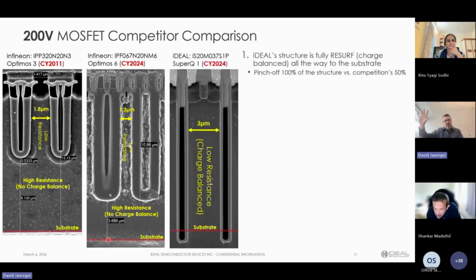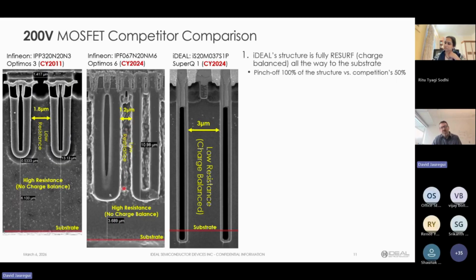Our technology, taking that 650 volt MOSFET structure, bringing it down to 200 volts. Here's what you get. There's our 3 micron mesa with a 1 micron trench, and you can see our mesas are wider. We're actually going into the substrate, so we don't rely on a high resistive material underneath the structure, and that allows us to have this leadership position in on resistance. But more importantly, you look at the structure and you think, okay, where are you going to go next? Half a micron, a quarter micron? You look at this, only about 28% of the conduction area is being used, whereas the rest of it is being used to block. It just becomes a structure that follows that we're starting to run out of RSP improvement curves.